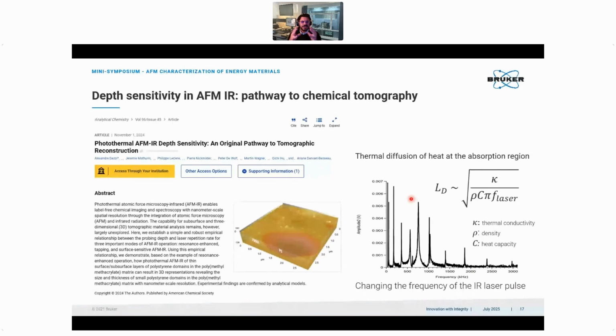So how does that translate? If you remember in this animation, the laser was pulsed to match an eigenmode frequency of the cantilever in contact, because we wanted to enhance our measurement. So if we adjust the frequency of the laser pulse at the high eigenmodes of this cantilever, then the laser pulse will be sent at very high frequency that could go up to a few megahertz. In that case, the heat wave does not have enough time to travel, so we have a very top-surface sensitive signal or measurement. And if we adjust the laser pulse to lower values, then we are more depth sensitive, right? And this is basically how we can get into this.